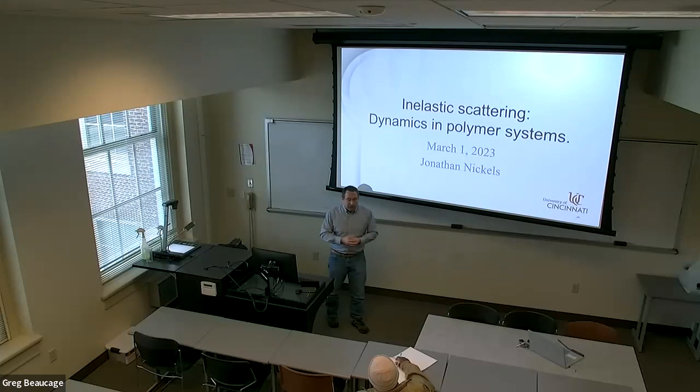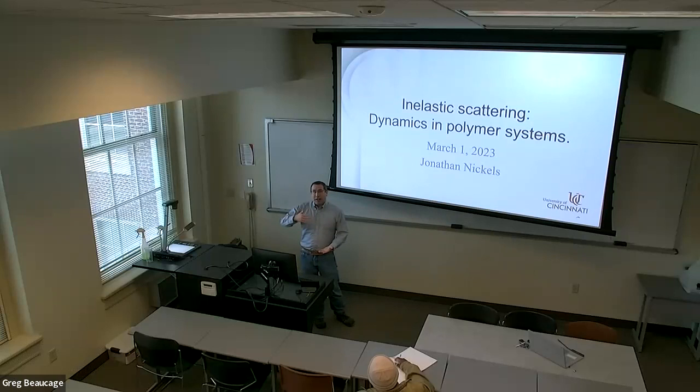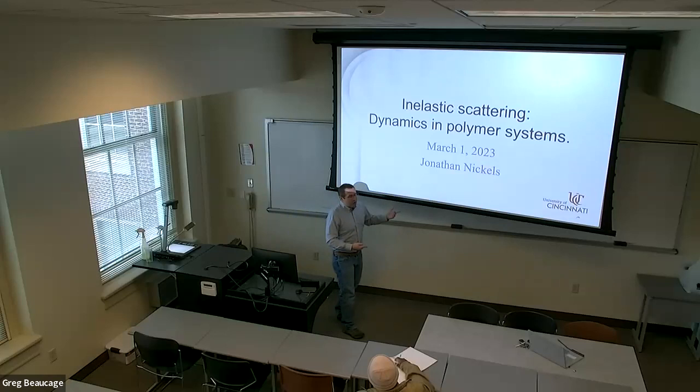And then we also look at some basic molecular motions of hydrogen bonding liquids. So water is a hydrogen bonding liquid. If we think about where the viscosity of a liquid comes from, you can think about this as a structural rearrangement. If you take the Green-Kubo approach, you think about a liquid, if you took an instant snapshot, there's some sort of percolated network that resists compression, right? So the resetting of the shear stress network could be understood to be the relaxation time of the system. If you look at the correct relaxation time, you could understand the time scale of the resetting of the network, and that would give you a relationship between the elastic modulus at infinite frequency and the relaxation time of the network. So if you understand that for a hydrogen bonding system, then maybe we can generalize some rules for that kind of thing. That's the other project I'm working on.